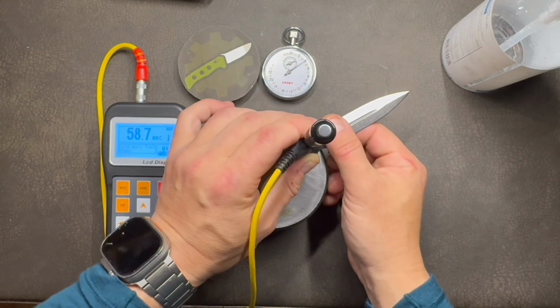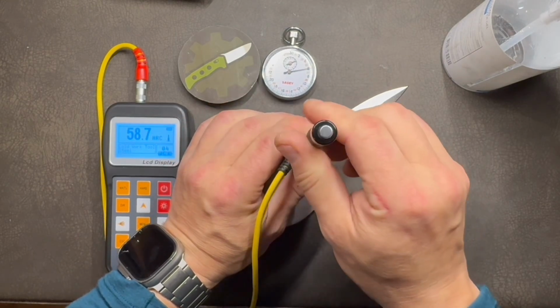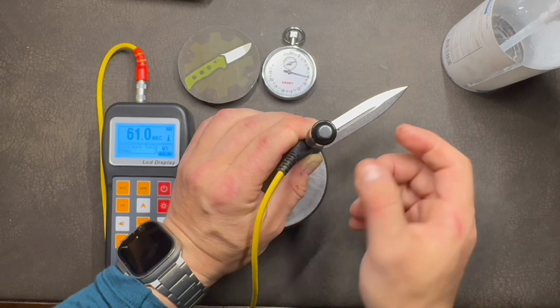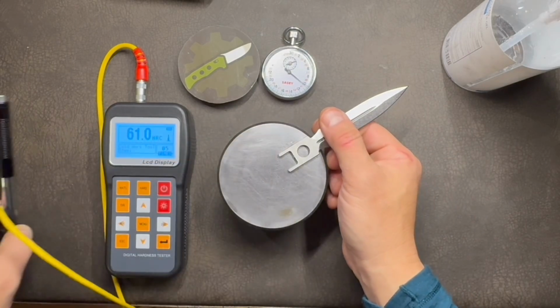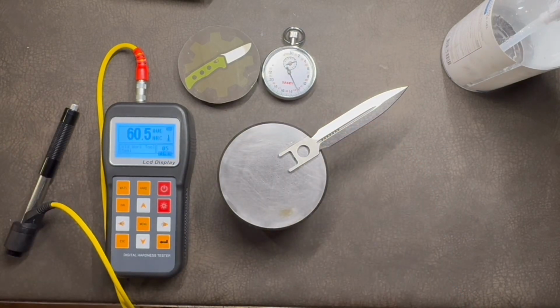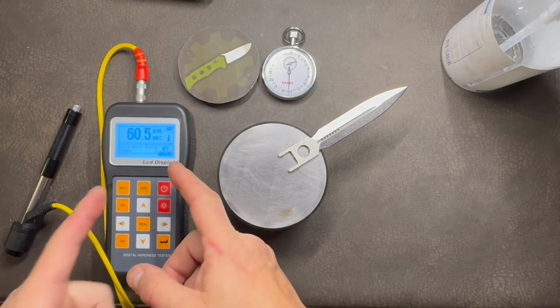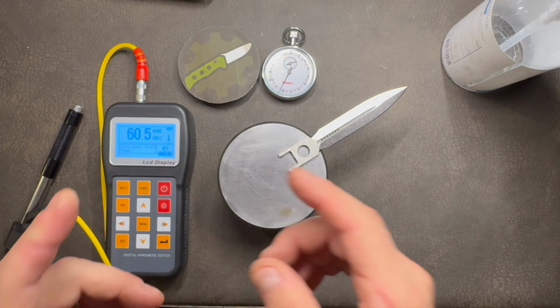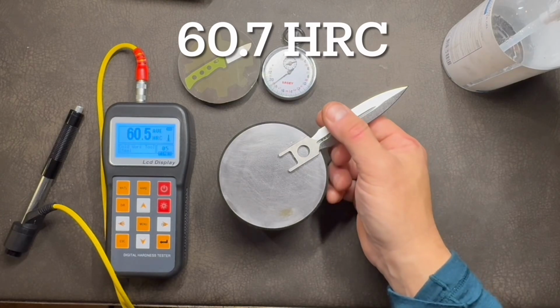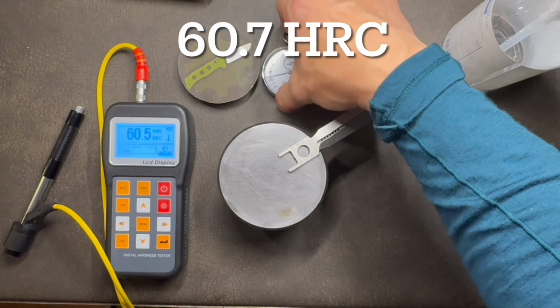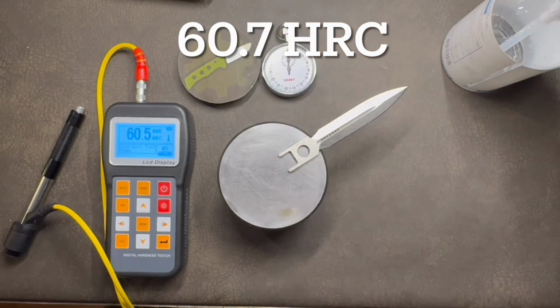And here's another outlier. Mathematically, it's outside the Six Sigma window. And that means I will have to recalculate the average again. And what I get this time is 60.7 HRC. Final verdict, 61 plus minus 0.5 HRC.